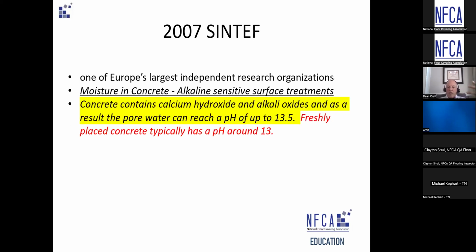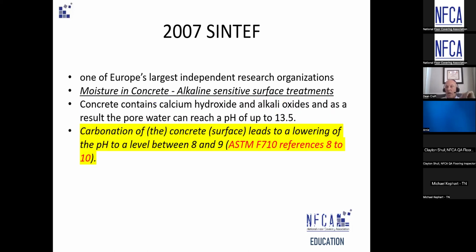And what they notice is obviously concrete contains a lot of hydroxides and alkalis, all those things that raise the pH. And they say typically around 13. I mean, fresh concrete is very, very caustic. It will eat a hole in your skin. But again, just like F710, it does say that the surface of the concrete is going to carbonate. Those hydroxides will react with the carbon dioxide, forming carbonate, and it'll lower the surface of the concrete to make it not detrimental to adhesives. And F710 references 8 to 10, but they're very similar.